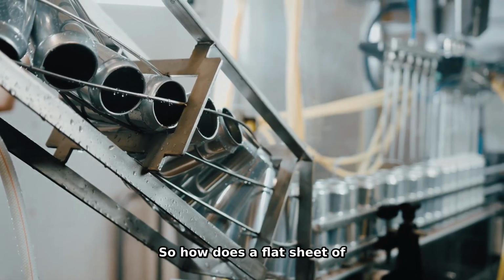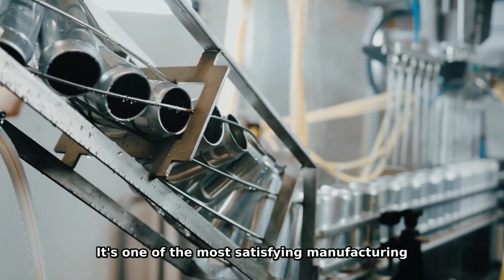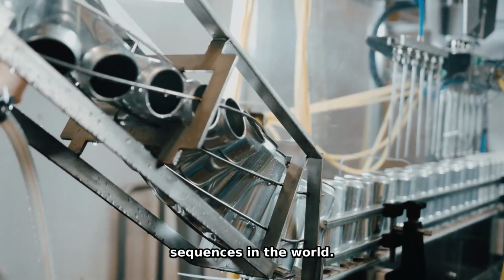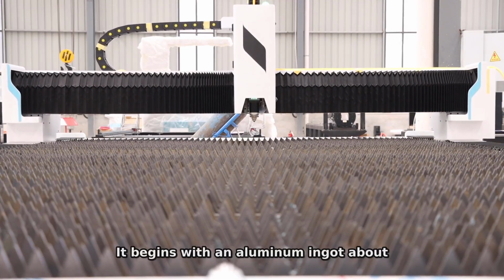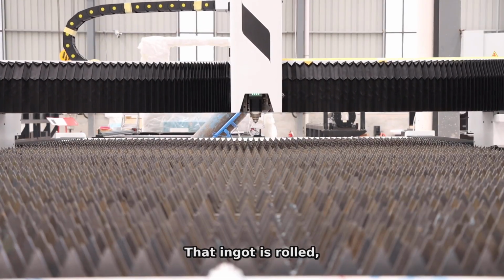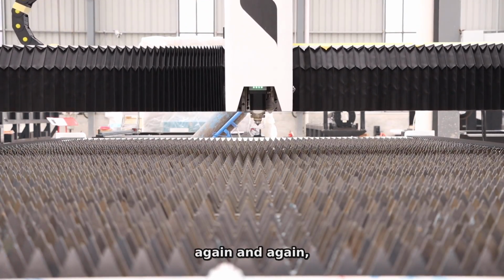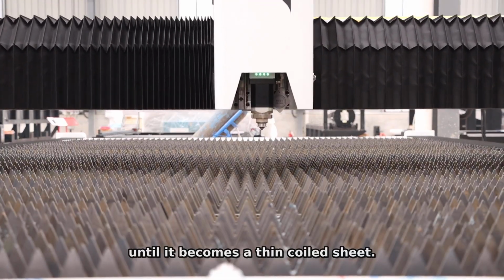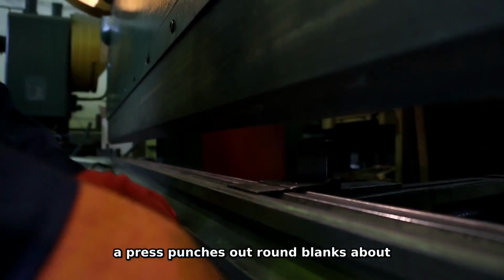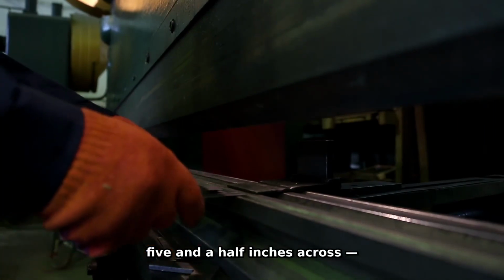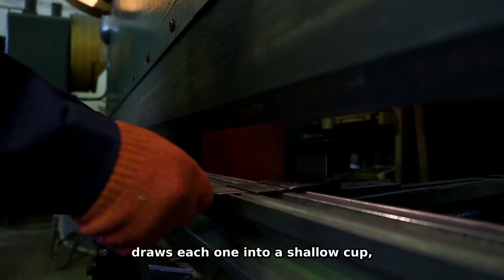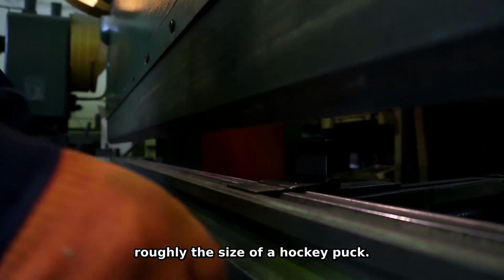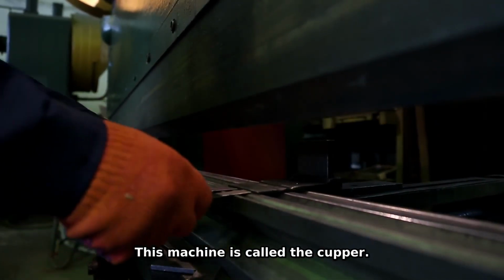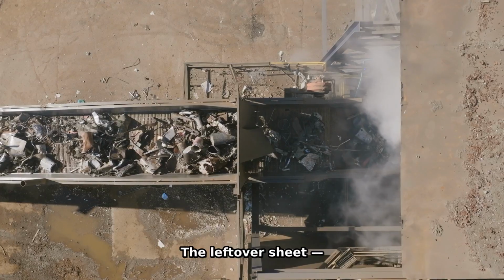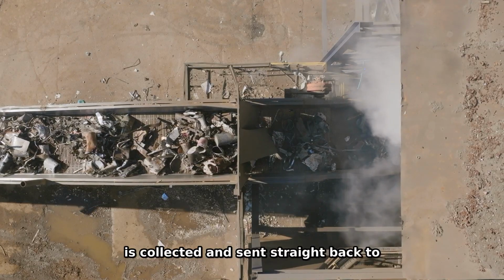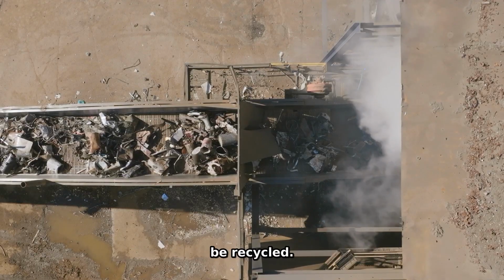So how does a flat sheet of metal become that perfect cylinder? It's one of the most satisfying manufacturing sequences in the world. It begins with an aluminum ingot about 30 inches thick. That ingot is rolled again and again until it becomes a thin coiled sheet. From that sheet, a press punches out round blanks about 5.5 inches across, and in the same motion, draws each one into a shallow cup, roughly the size of a hockey puck. This machine is called the cupper. The leftover sheet, a skeleton full of holes, is collected and sent straight back to be recycled.